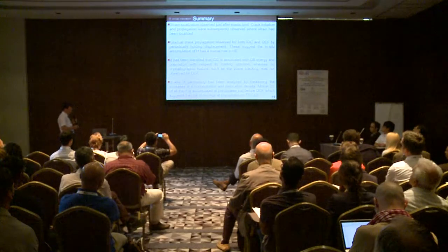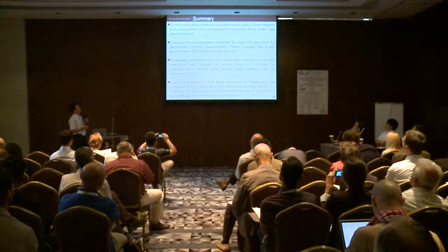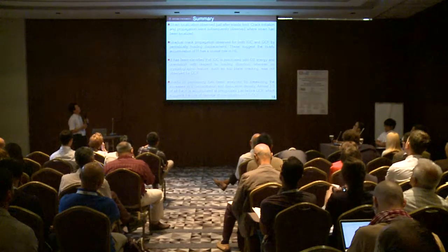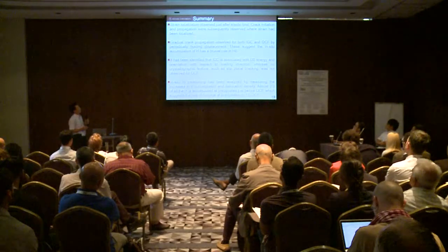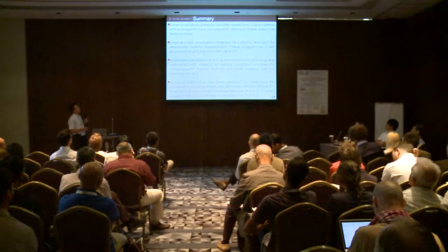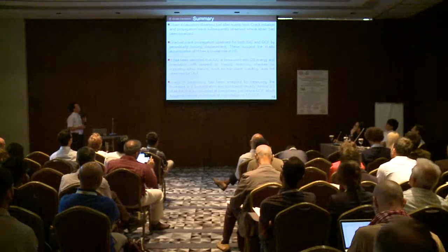Okay, with that, I would like to summarize my talk. Strain localization was observed just after the elastic limit in this case, and crack initiation and propagation was subsequently observed where strain had been localized. And fairly gradual crack propagation was observed for both intergranular cracking and quasi-cleavage fracture, which are very different from the